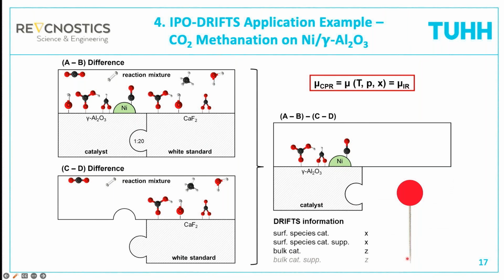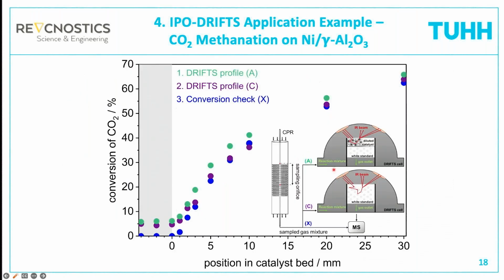So we have removed the haystack and we see only the surface species sitting on the catalyst, on the nickel particle, on the catalyst support, on the gamma alumina, and maybe absorptions on the bulk catalyst and the bulk catalyst support, but with respect to the reference state, which is the catalyst in pure hydrogen, so probably metallic nickel. And now we just have to make sure that we are approaching isopotential conditions.